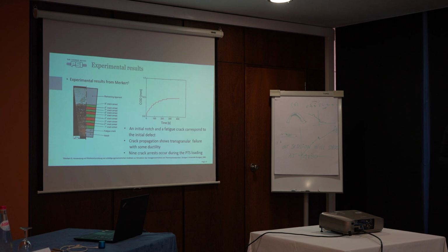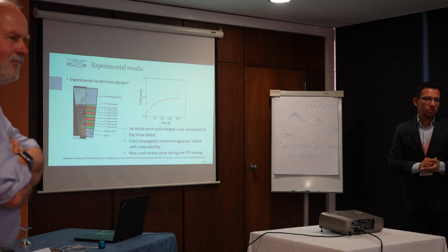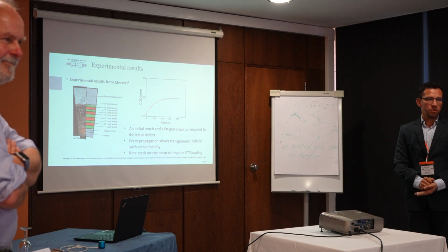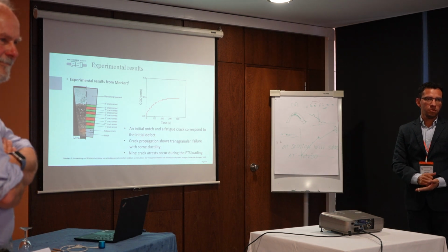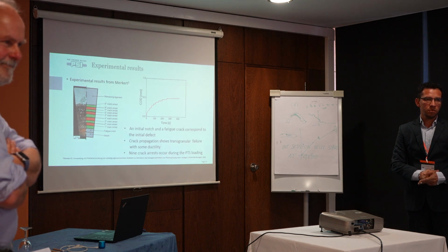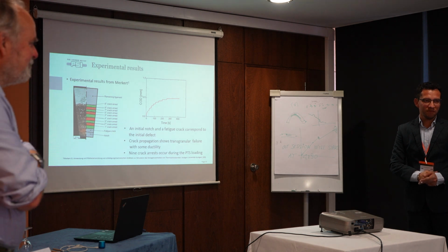I suggest a comment, supporting what was said before. You could have easily calculated the size of the plastic zone, and then it would be easier to answer whether you can stay within the domain of the linear elastic analysis. I definitely would consider elastoplastic analysis for 250 degrees at this level, but okay, it's your future work.